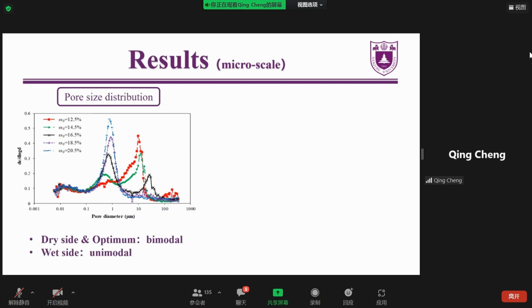This is because for the soil samples compacted on the dry side and at optimal water content, the clay particles assemble together and the aggregate structure is well developed. However, we can find that for the soil samples compacted on the wet side, the pore size distributions show a unimodal form. This is attributed to the assembly of the clay particle matrix around the silt grains and the gradual formation of a dispersed structure.